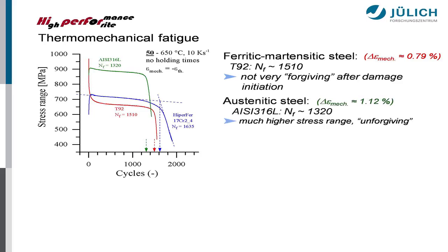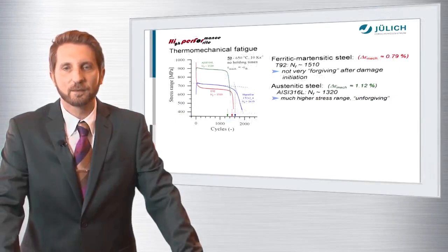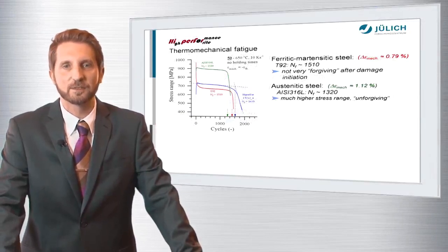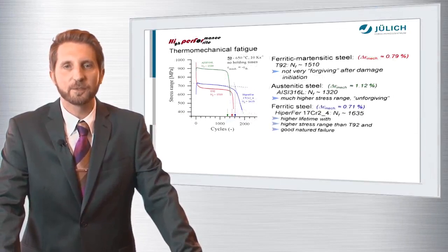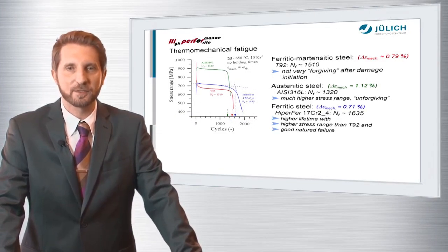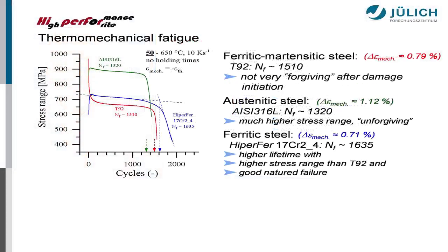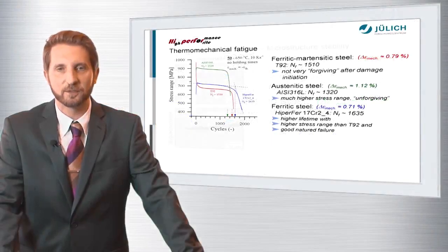In case of the austenitic grade, here alloy 316, that's represented by the green curve. You see that this material performs completely different. You do have pronounced hardening in the initial phase. You again enter a stable phase, and after approximately 1300 cycles, damage comes rapidly too. So obviously this material seems to be unforgiving too. And the blue curve represents our new ferritic hyperfer 17 chromium 2.4 grade. And this one reaches higher lifetime in combination with higher stress range than, for example, the ferritic martensitic grade. And it seems to have more decent failure behavior, which is quite positive.